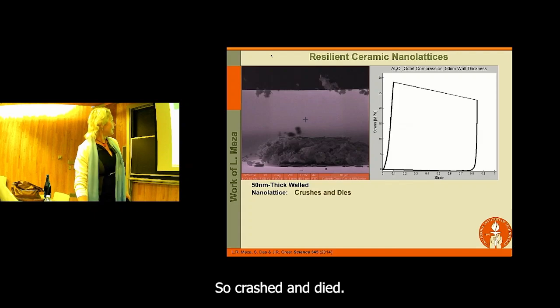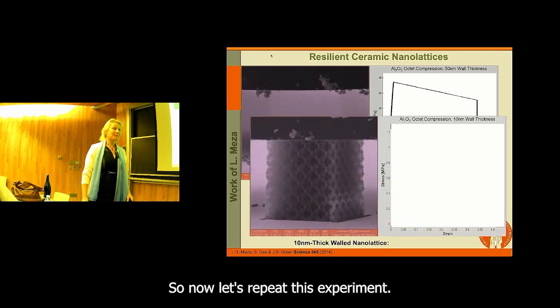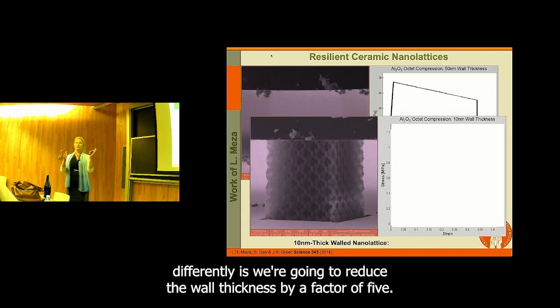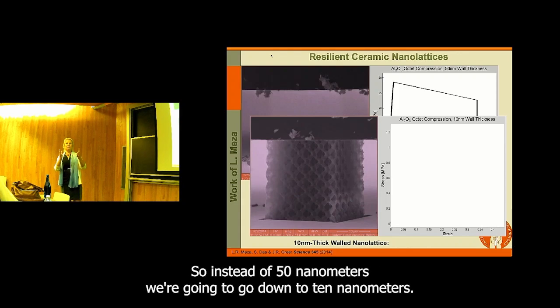So it crushed and died. So now let's repeat this experiment. And the only thing that we're going to do differently is we're going to reduce the wall thickness by a factor of 5. So instead of 50 nanometers, we're going to go down to 10 nanometers.